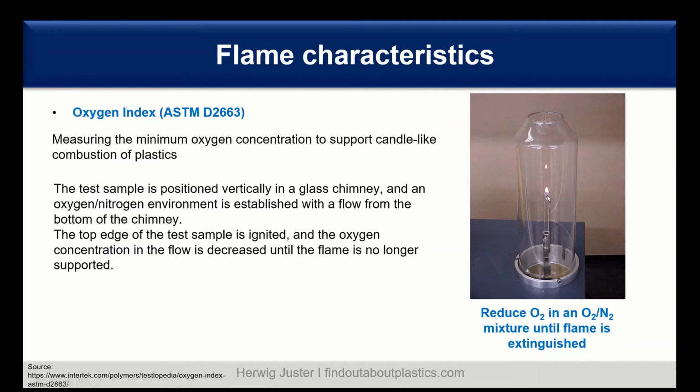We ignite the sample, and in this chimney we have an oxygen-nitrogen concentration, and then step by step you start reducing the oxygen until the flame is extinguished, and then you get this oxygen index.